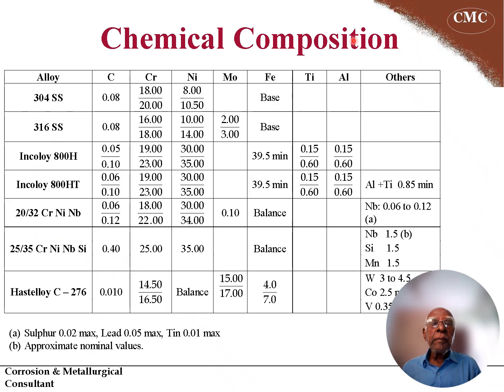These are the chemical compositions of the alloys I mentioned in the previous slides. The most important thing to notice is the chromium. I am comparing the elements with the common stainless steel, which is called 304 SS, and the somewhat higher 316 SS. In these alloys, you can notice that chromium goes up to 23, with a minimum of even 19 in some, as compared to 8% nickel in 304 SS.